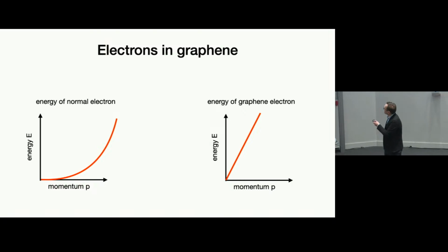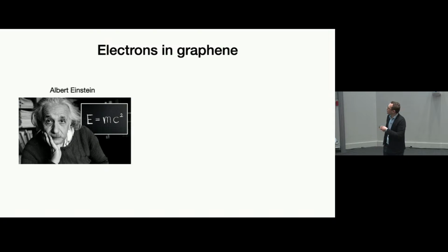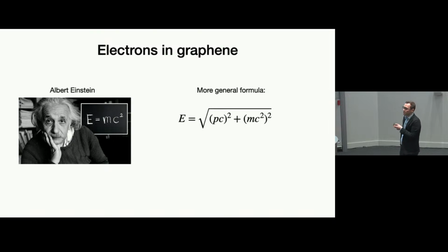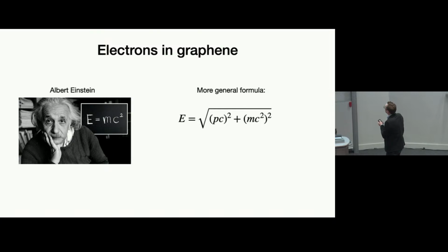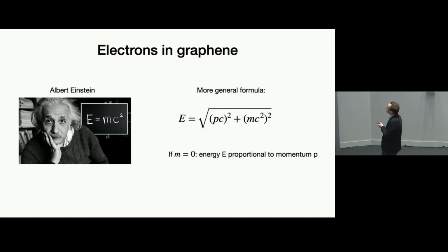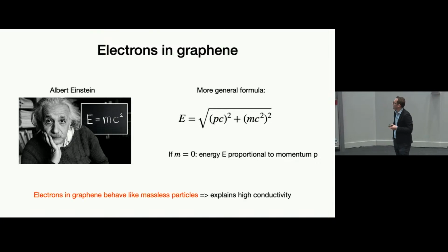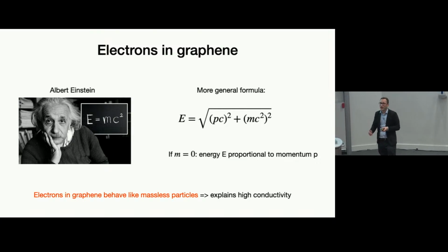And to understand why this is so special, we have to go back to this gentleman, Albert Einstein. You have probably all seen this formula: E equals mc squared. It means the energy of a particle is equal to its mass times the speed of light squared. Now this actually is a formula that only applies to particles that aren't moving. So if you want to calculate the energy of a moving particle, you have to use a more general formula. It's this one, which involves the momentum p. Now when we look at this formula, and we look at the special case of mass equals 0, so a massless particle, we can see that the energy will be proportional to the momentum in that case, which is exactly how the electrons in graphene behave. So in other words, the electrons in graphene behave as if they didn't have a mass. They behave as massless particles, and that explains why they have such a high electrical conductivity.